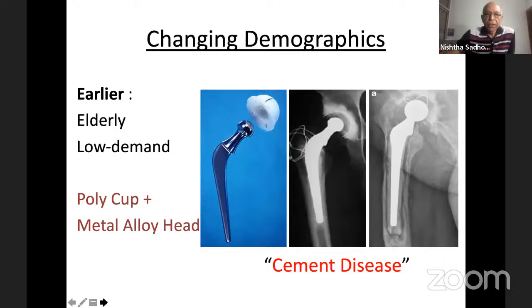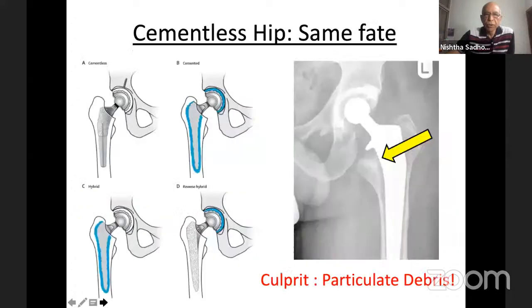So the changing demographics of the hip. We have come a long way from the Charnley days, when it was generally a preserve of the elderly with low demand, and there was a poly cup and the metal alloy head. But what generally would happen is that it would eventually get loose. So we have this loosening of the prosthesis, which at that time was erroneously termed as cement disease. It was attributed as a characteristic of cement that the prosthesis became loose.